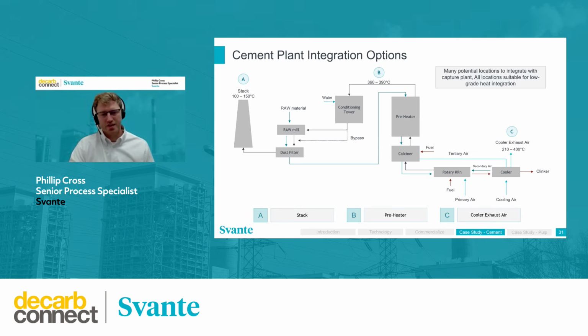So the moisture content can change the heat availability from the site, and it can also require additional energy for drying. And lastly, the mode of operation of cement plants. So they can have the raw mill on or off, and vice versa. And this can have a significant impact on the air ingress, consequently the CO2 concentration and the temperature of the flue gas. And the plant age is also a factor that we need to consider when we're looking at deploying carbon capture on cement plants. So older plants can be more challenging to control this air ingress, and you can see CO2 concentrations as low as 14%.